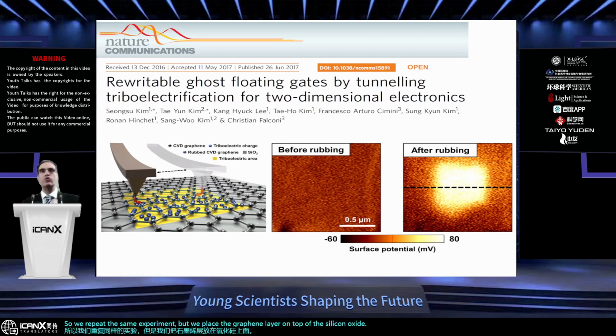So apparently, one could think that after rubbing, that means creating triboelectric charges, there will be no potential difference, because graphene, in a way, is conductive, and therefore it should not allow localized charge to survive. The potential difference should disappear because of the conductivity of the graphene. But actually, as you see here, we found that after rubbing, there was significant potential difference, similar to the previous work from Professor Wang.